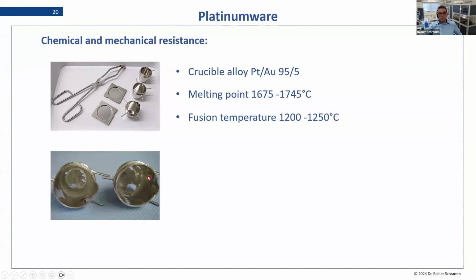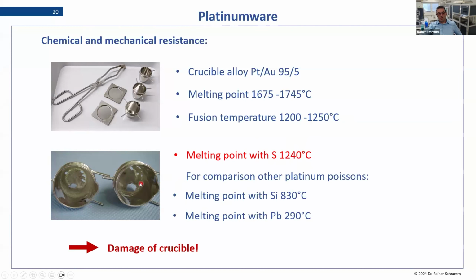However, if you have in your sample metallic parts or reducing particles, then this will fail because immediately it will reduce the melting point of your platinum ware to a lower one. And if you come in the range of your fusion temperature, it will destroy your platinum ware. Some examples: sulfide, so not sulfate, it's sulfide, S2 minus, which reduces that, or metal silicon, metal lead, they will extremely change the behavior. And then you have, like in this picture, holes in it.